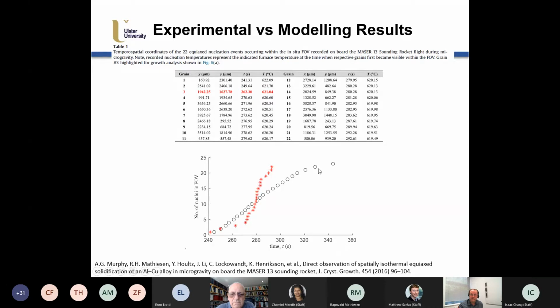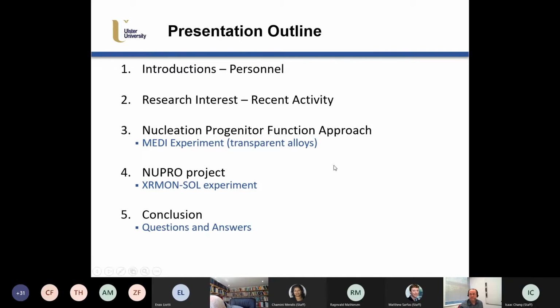The white circles are the predictions of nucleation events within that field of view, and the red here is what was actually measured. So the rate's a little bit higher in the real experiment. We're both getting to around 22. We're both getting exactly 22 nucleated crystals within the domain. I do have an idea as to why this is a little bit slower, and I would like to work on this going forward as well.